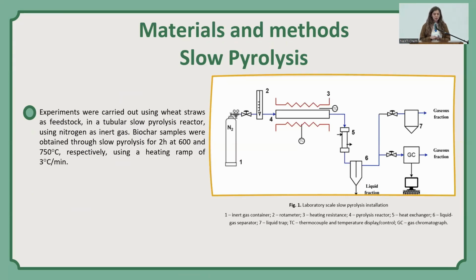For the first experiment, the slow pyrolysis, our experiments were carried out using a tubular slow pyrolysis reactor, where we use nitrogen as inert gas and wheat straws as feedstock. The biochar samples were heated at 2 temperatures. Here we used 600 Celsius degrees and 750 Celsius degrees, and maintained at this temperature for 2 hours to allow the reaction to take place.